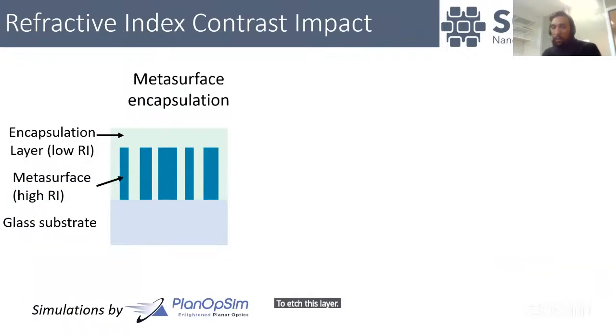So now if we come back to the refractive index range that we can cover, why is it important to have such a refractive index contrast? Usually when you work on a metasurface, the base building component is what we call a meta-atom. So you have these pillars, usually of high refractive index materials, and you play on the dimension to have a full coverage of the phase and develop your metasurface.